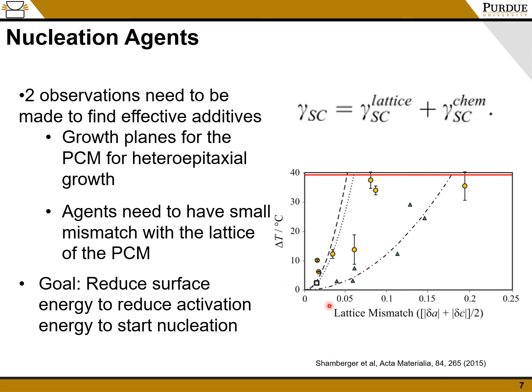You can see in this graph down here, these triangles represent different nucleation agents. And the ones that had very small lattice mismatch had reduced the supercooling from 40 degrees down to below 10 degrees, whereas nucleation agents that had more lattice mismatch did not reduce the supercooling nearly as much.